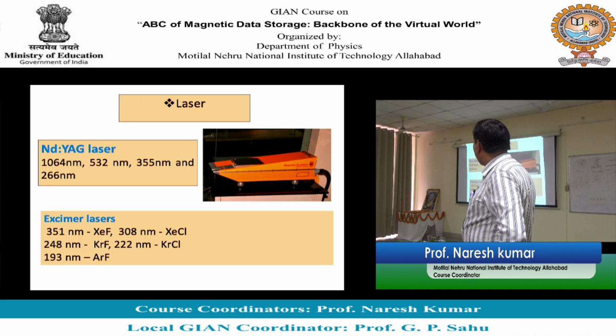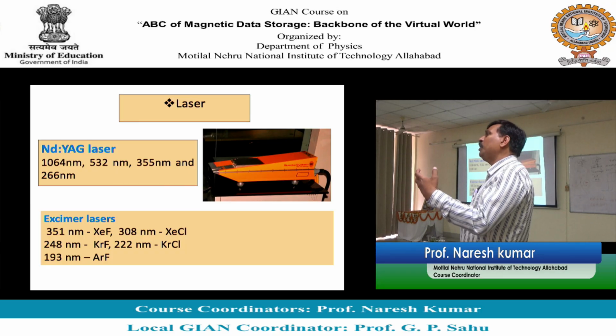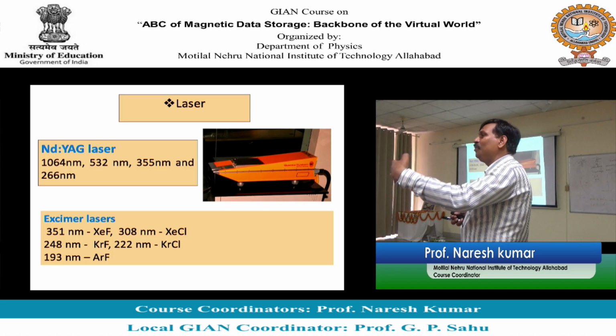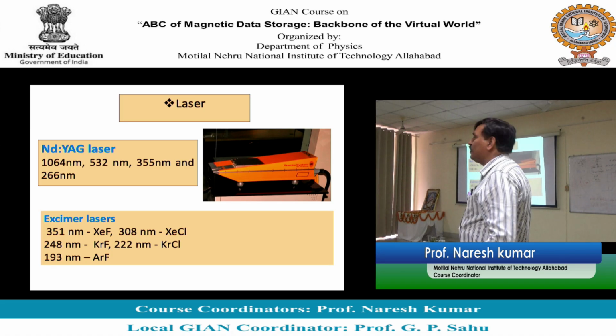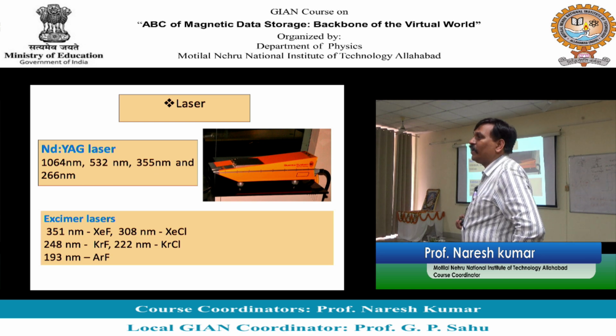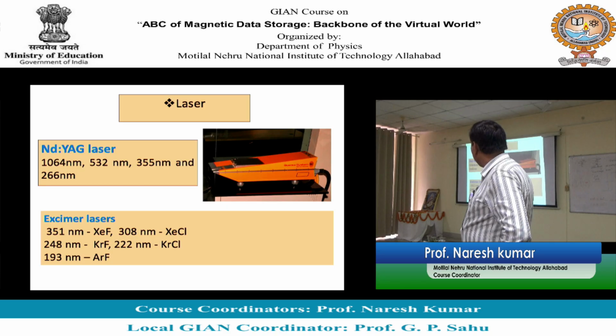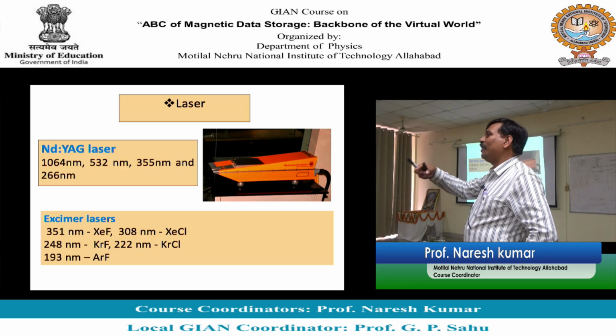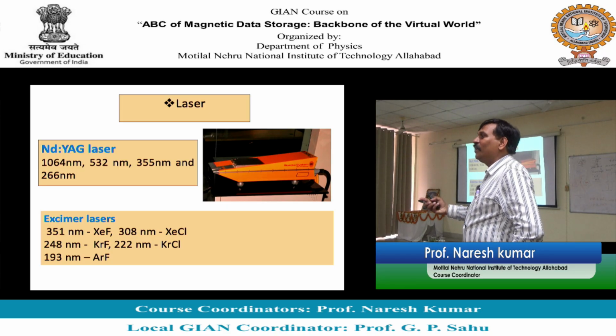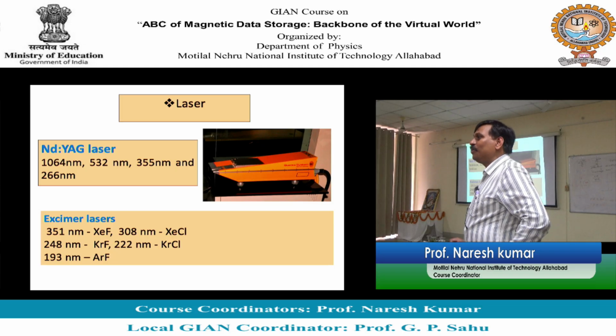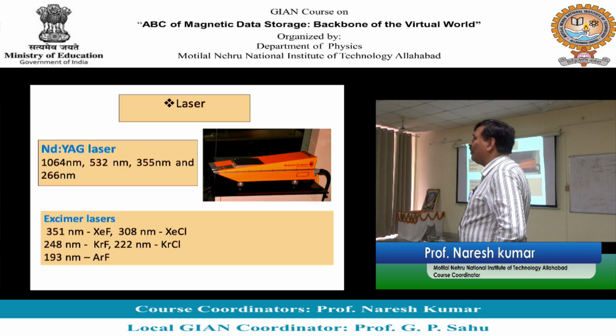This is the fundamental mode. If you go from fundamental to the second harmonic, you have 532, which is in the visible range. For the third harmonic, you have 355. For the fourth harmonic, 4 omega, you have 266. So depending upon what kind of target you want to ablate, you have to choose these wavelengths accordingly. For oxides, we recommend that you use lower wavelengths like 266. But the moment you look at the harmonics, second, third harmonics, the intensity goes down like anything. So if you are working with 266, the energy will be very, very small.